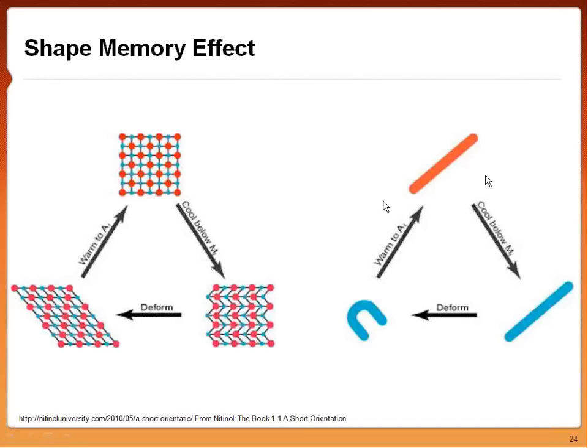And you can see that in a piece of material again when you take a red bar, being the hot material, cool it to blue, cold, deform it, and heat it back up, it comes back to shape. So that's the shape memory effect. However, we also heard that nitinol exhibits superelasticity. Basically, you can crush it and it comes back to shape pretty easily with enough applied force.